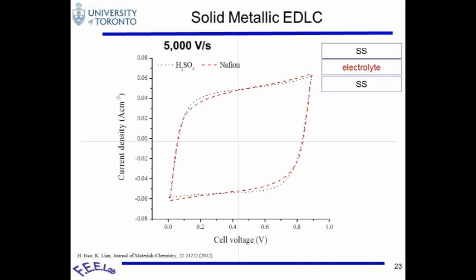The black one is 5 molar sulfuric acid, and the red one is the Nafion as pristine condition. These have been cycled at 5,000 volts per second, which is the highest rate that the machine, the potentiostat, can reach. These two look very close to rectangular, and this is an super ultra high rate. So this is very encouraging.